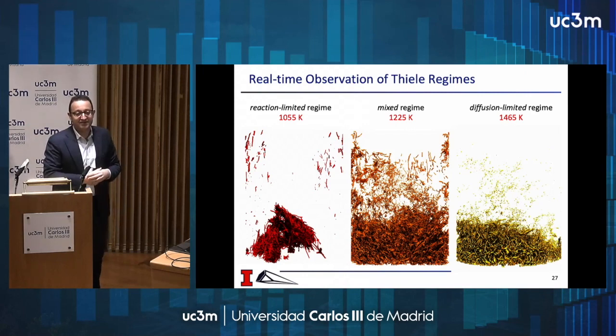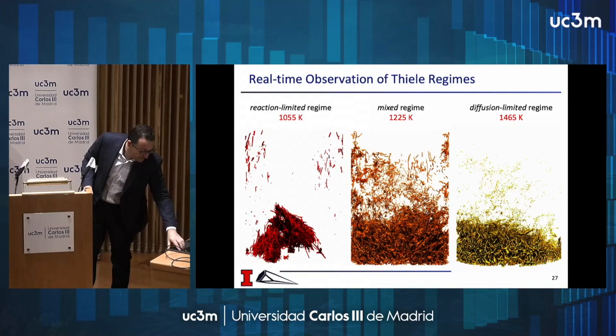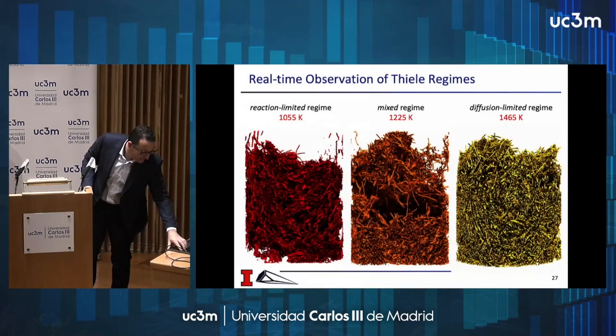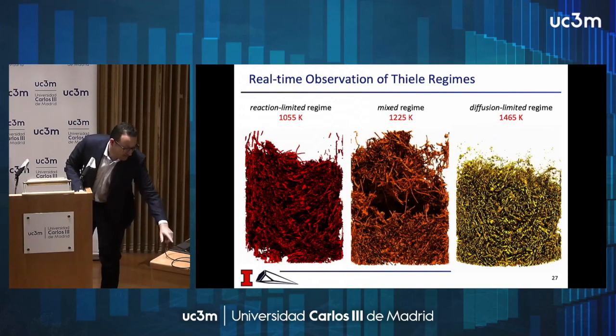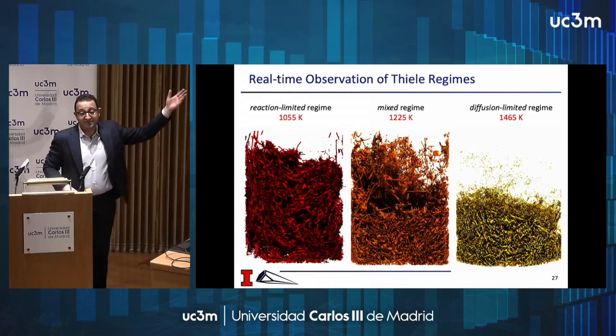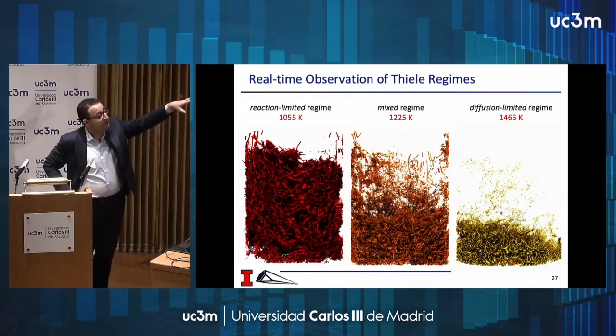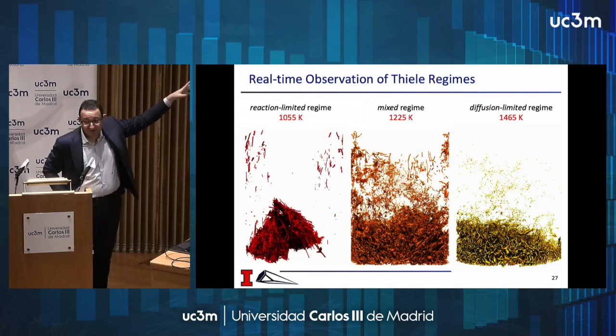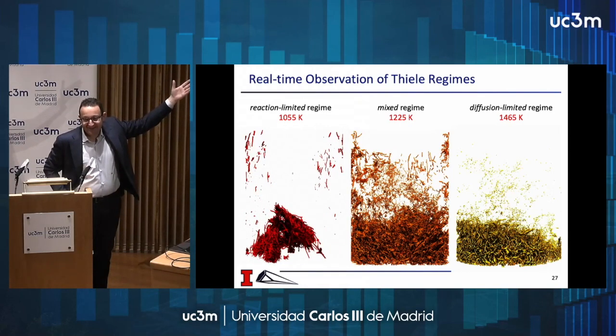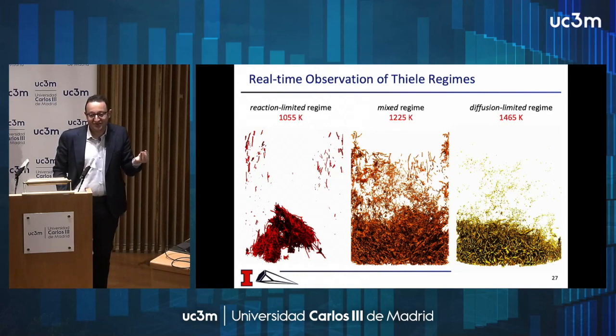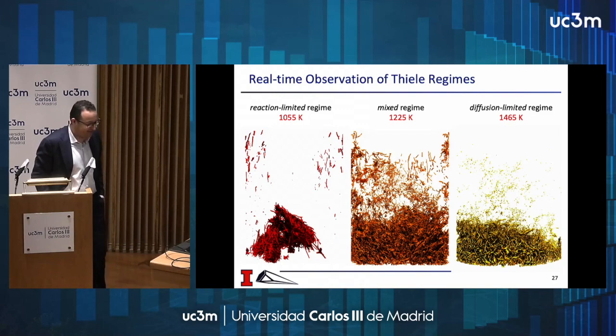It also has a very big significance for atmospheric entry. If you think about this in terms of actual hypersonic flight, the part on the right is when you are at high temperature, and the part on the left is when you are at low temperatures, where you would think that you're actually safe. But you see that the low temperature regime is where the material decomposes in the interior, and the thermal protection system loses structural strength. And so this is an important finding that we're trying to quantify a little bit better right now.